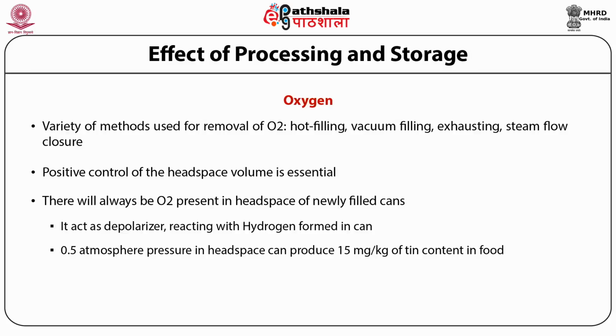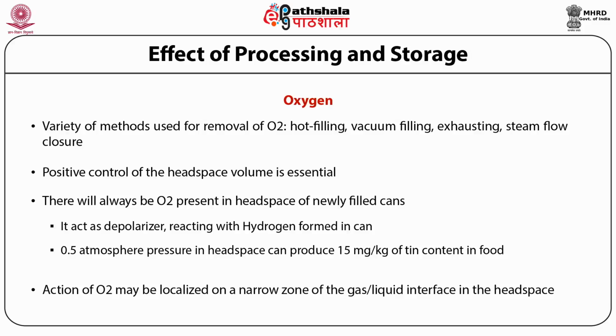Although this is a relatively small amount in comparison with the total coating weight, the action of the oxygen may be localized on a narrow zone of the gas or liquid interface in the headspace. This may result in the production of an unsightly etch line, even exposure of an area of steel much larger than that exposed at pores in the initial coating.